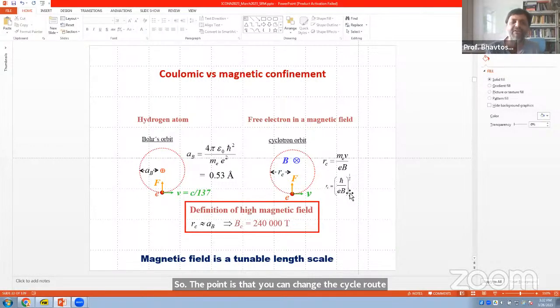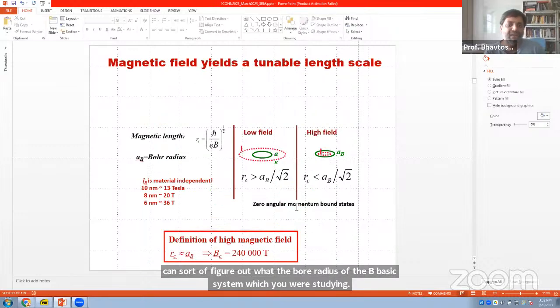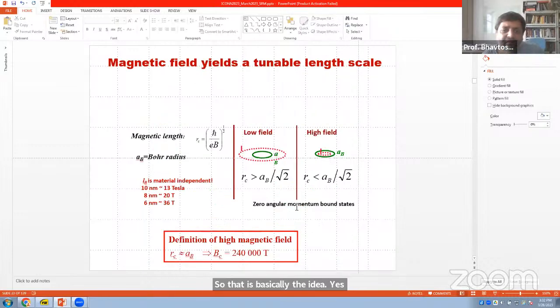When the cyclotron radius becomes comparable to the Bohr radius, the magnetic field becomes a strong perturbation on the orbit. And by seeing how the energy levels shift as you apply this large magnetic field, you can figure out what the Bohr radius and the binding energy of the basic system you were studying are. So that is basically the idea.